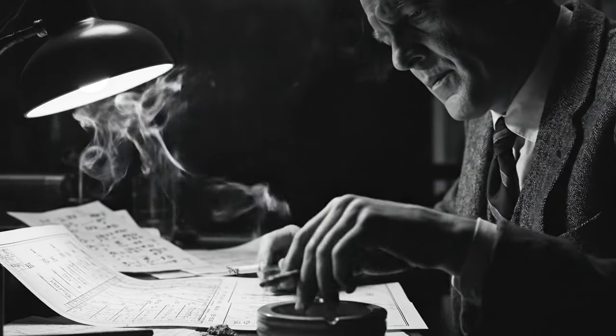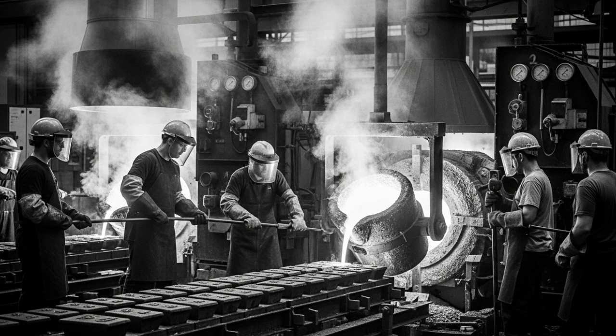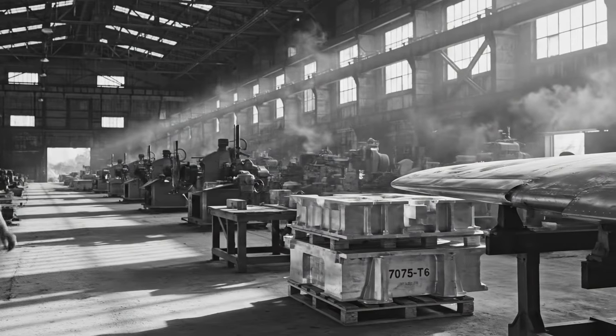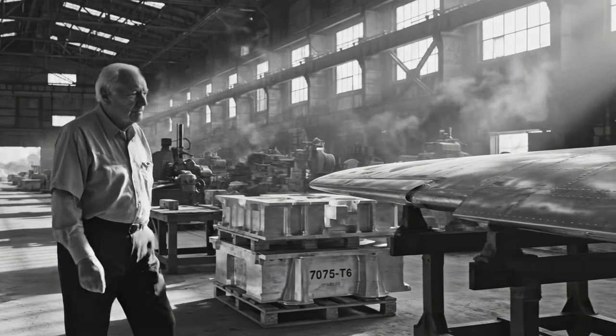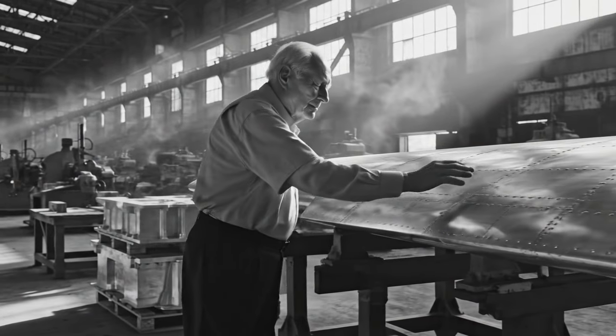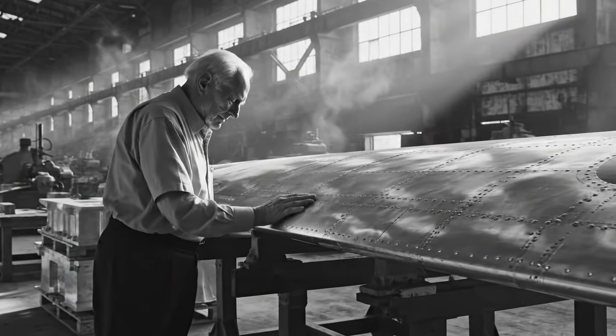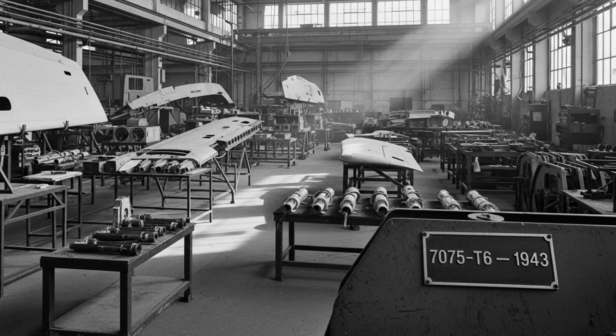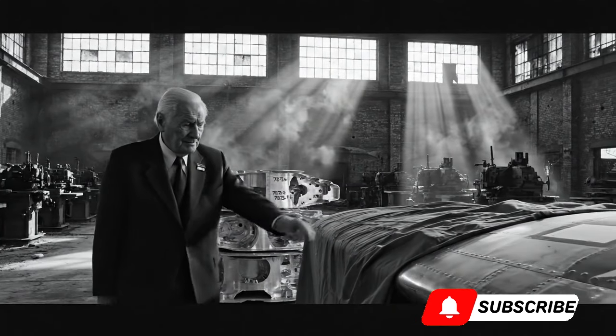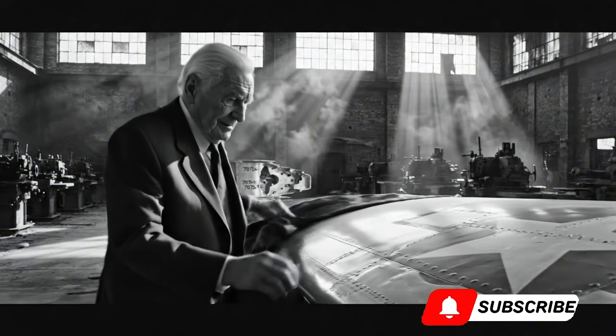They failed. The ingots showed internal segregation. Zinc and copper compounds were concentrating unevenly throughout the material rather than distributing uniformly. Under stress testing, they fractured in ways that were predictable but unusable. The team regrouped. Hertzberg issued a memo. The problem wasn't the alloy composition. It was the ingot casting temperature and cooling rate. That margin of error had to be narrowed from plus or minus 50 degrees to plus or minus 8 degrees during the casting process.